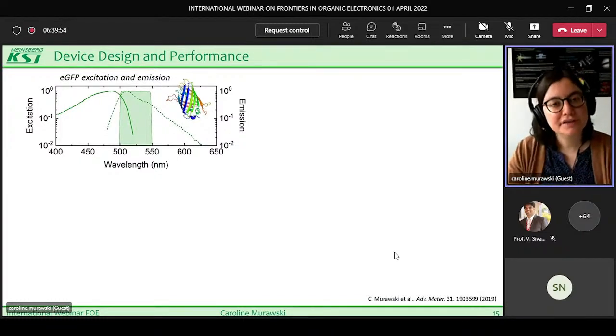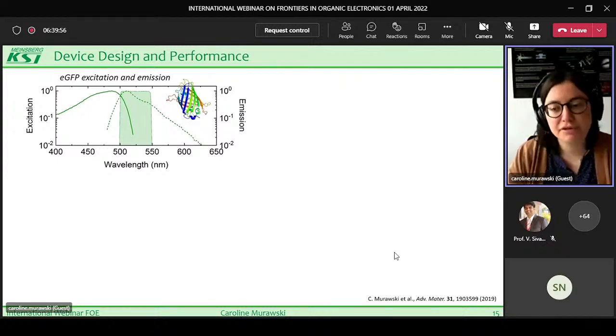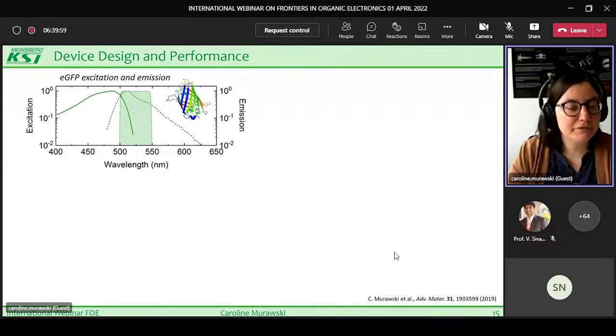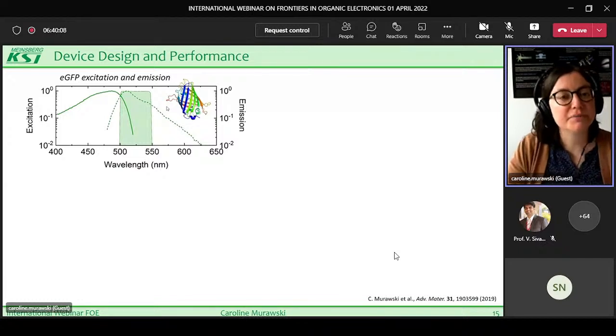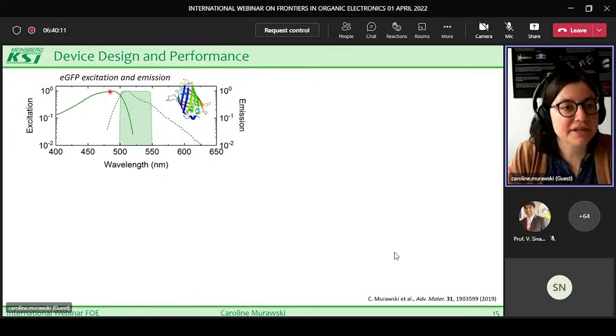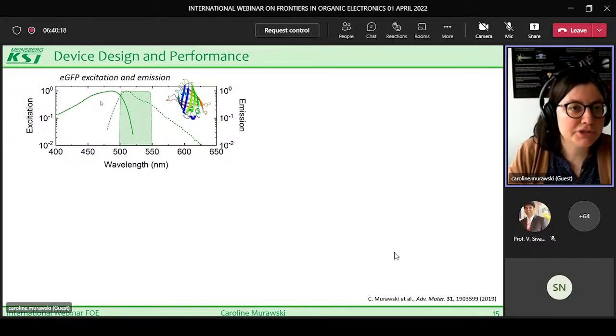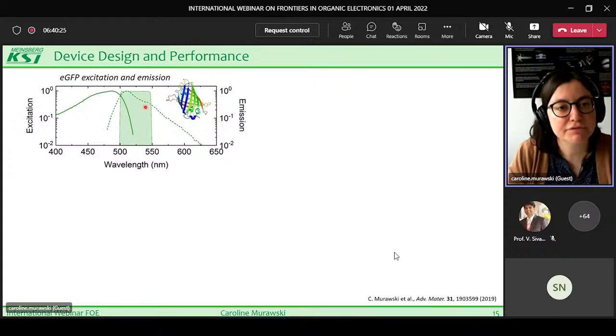So in order to design OLEDs for this purpose, we first need to have a look at the excitation spectrum of the typical light-sensitive proteins, and we specifically focused on the green fluorescent protein shown here, which is one of the most common ones. And you see here the excitation spectrum and the emission spectrum of this fluorescent protein. So usually one would use a blue laser or so, excite here, and then filter out just the emission between 500 and 550 nanometers to look at the emission from the fluorophore.